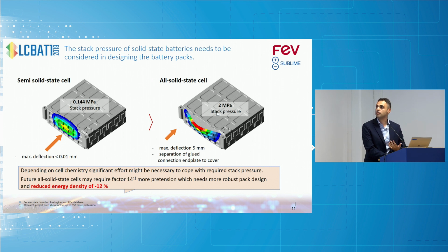I think this is the Samsung cell, an anode-less cell that operates at 2 megapascal, a very low pressure. By just applying this pressure at the pack level, our team calculated that you have to work with a more robust pack design, and you lose energy density by 12%. So this is also something we have to consider at the end, because this stack pressure, at the moment we don't care, we just want the cells to work, but it has a huge impact on the end user.